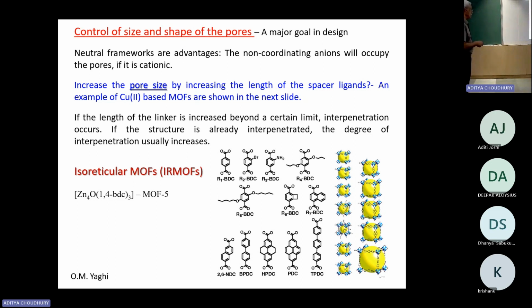Again, we have to go to Omar Yaghi's work, isoreticular MOFs. He called them isoreticular MOFs. Without changing the interpenetration, he can increase the pore size. How do you do that? From BDC, you put in some substituents, and at the same time he increases the length. Because he increases with substitution, the pore size increases. In all these, it's only a twofold interpenetration, nothing else. The interpenetration is constant, with no additional interpenetration.